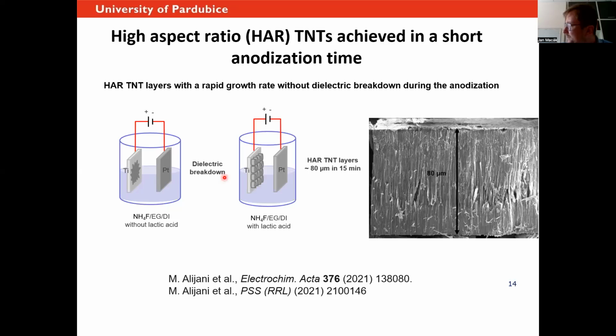And what will happen is that you will have some avalanche increase of current, the electrolyte will heat up, and at the end you will have something which is called breakdown. So the layers will lift off and everything will be damaged. And that's of course no way to go.